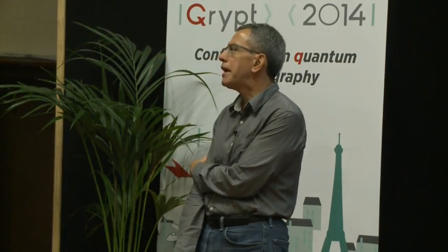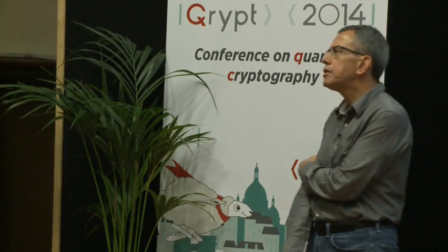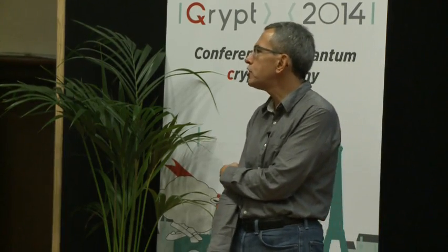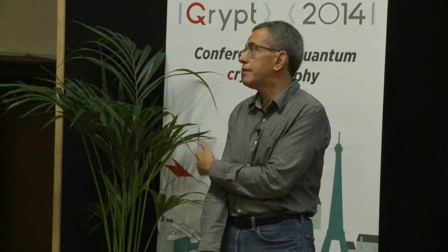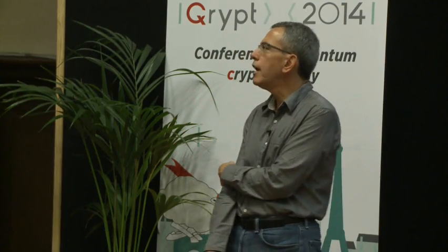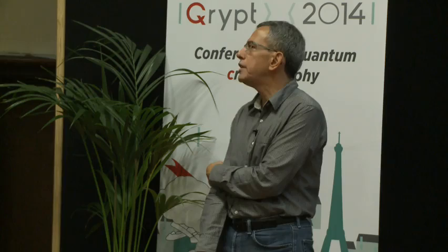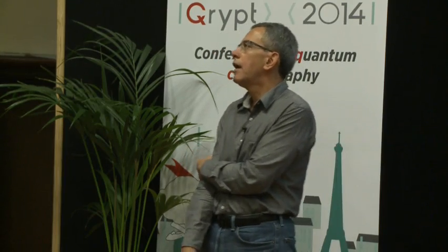So the wavelength of the photons in this case is 962 nanometers. Basically, without much of a change in the properties, one can have quantum dots ranging from 900 nanometers to 1 micron, possibly up to 1.2 microns. I'm saying possibly because of the detectors, or the lack of detectors until recently. Not many people looked into these redder quantum dots. Now that we have superconducting detectors and use them, we could in principle go back in this direction.